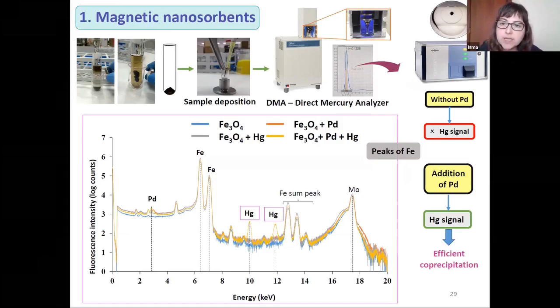However, we use TXRF as a characterization technique to see what happens with the mercury. For example, as we can see in the spectra, without using palladium, mercury cannot be detected. On the contrary, if we use palladium in solution, I think it's in a ratio of 1 to 50, not sure. I think it's 100 ppb of mercury in 5,000 ppb of palladium. So we can see the peak of mercury in that case, showing an efficient co-precipitation of trapping in presence of